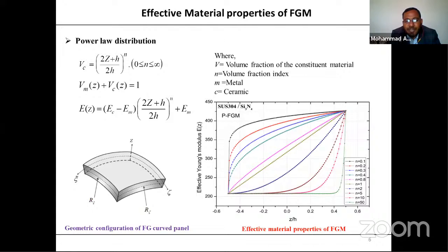So here we can choose the value of n for different materials. Like if we select n equal to 0, then it will purely behave as a ceramic material. This component will become 0, and by putting n equal to 0, this becomes 1. Em and Em get cancelled, and it will purely act as a ceramic component. And by putting n equal to infinity, we get effective material properties very similar to the metal. Here we can observe that for n equal to 1, it's just a straight line. But for different values of n, the effective material properties vary in the thickness direction.